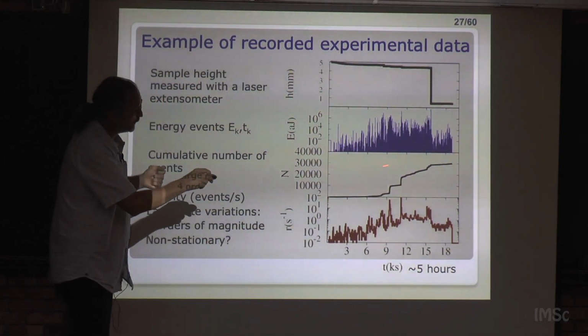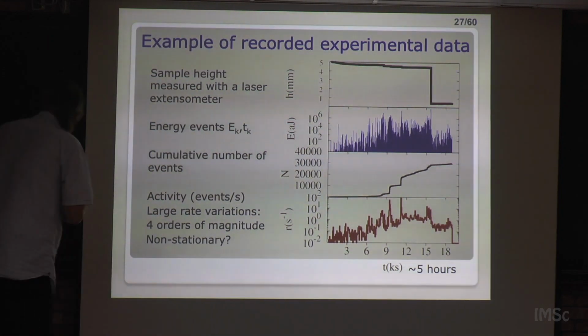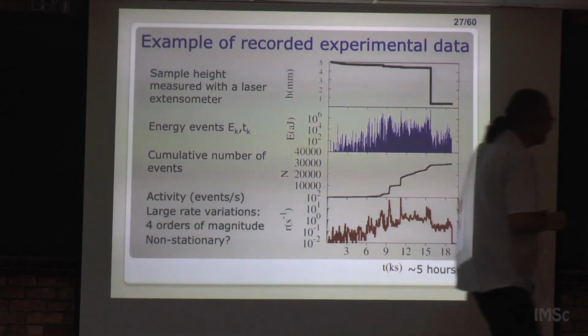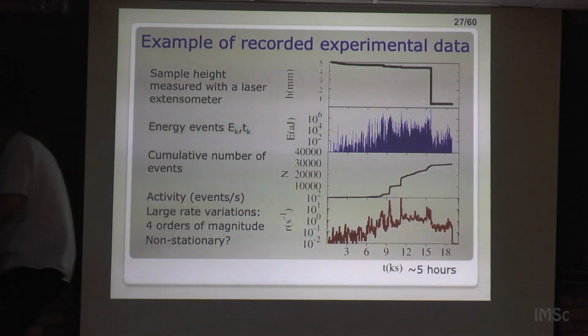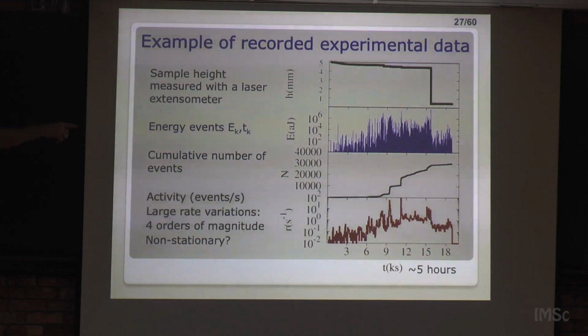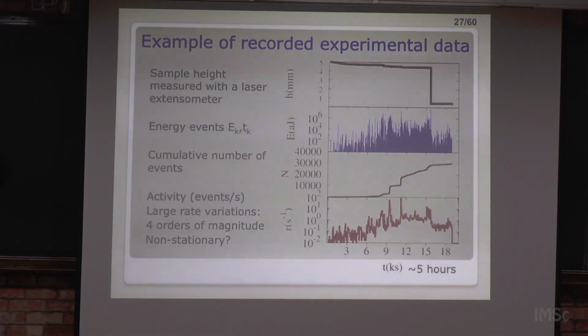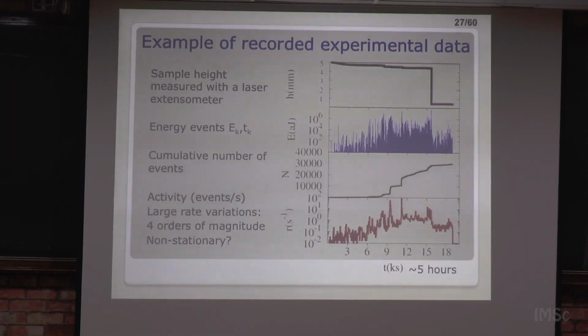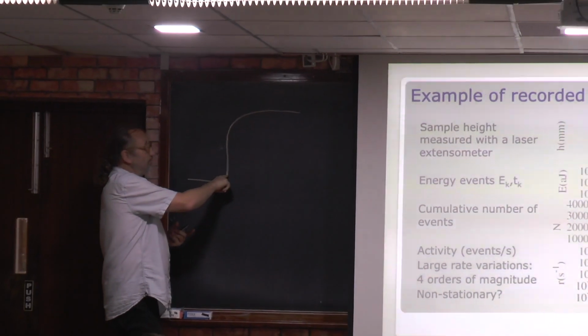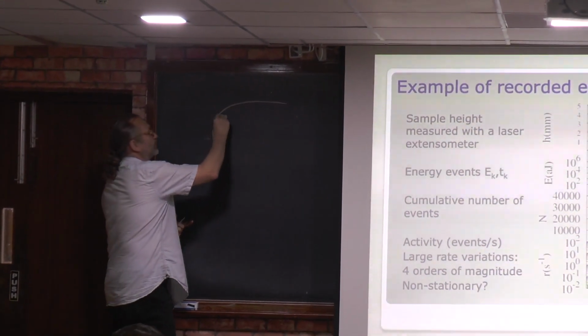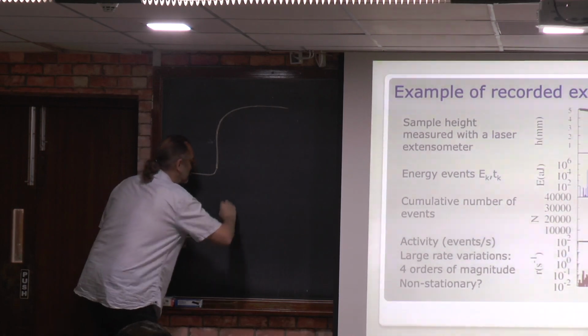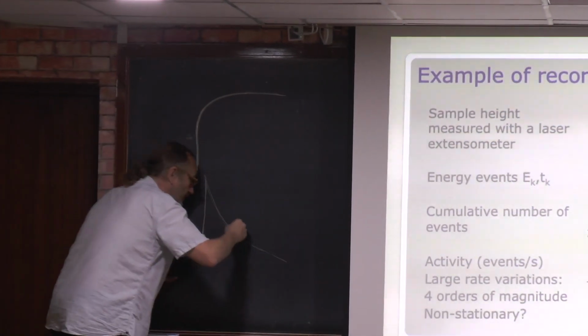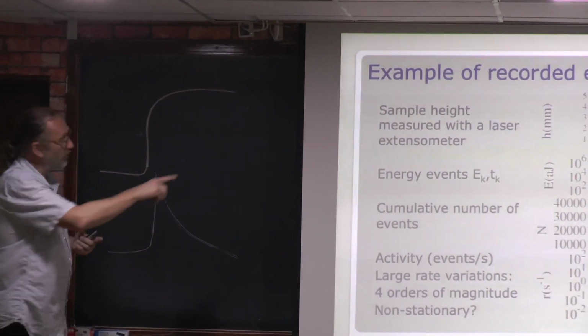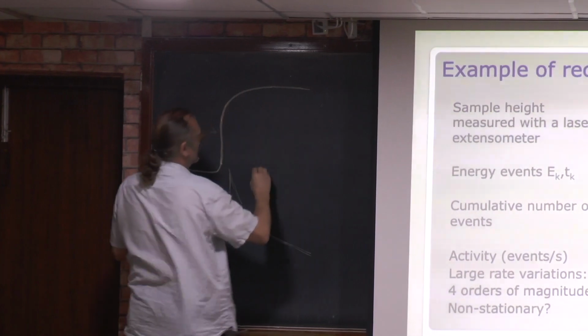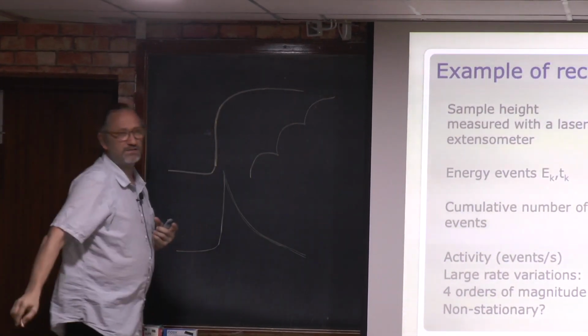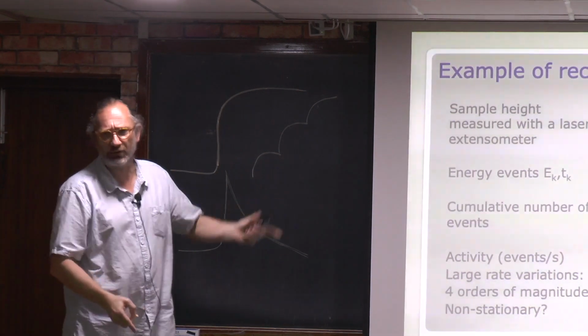And also, in this curve here, you already see the Omori law. Because when you see a cumulative curve that is like this, which means there were many events, and then after that there was this curvature, this means that the activity is like this. And this is nothing more than the aftershocks. So already here, when you have this kind of steps, it's not Poissonian. It cannot be a Poisson process at all.